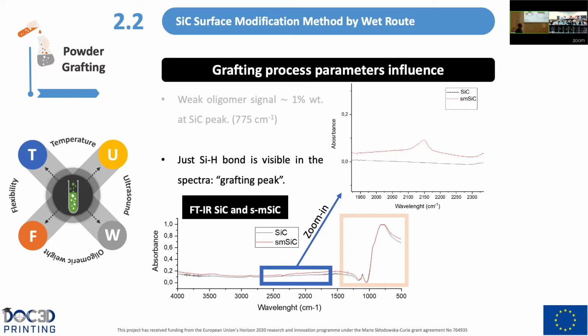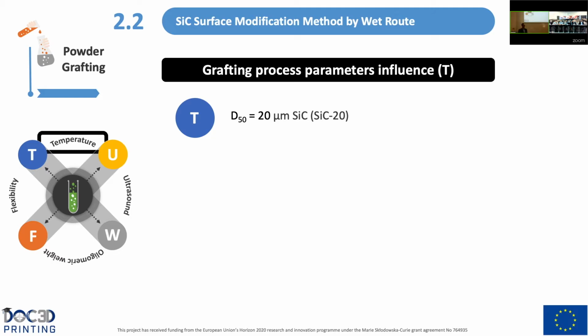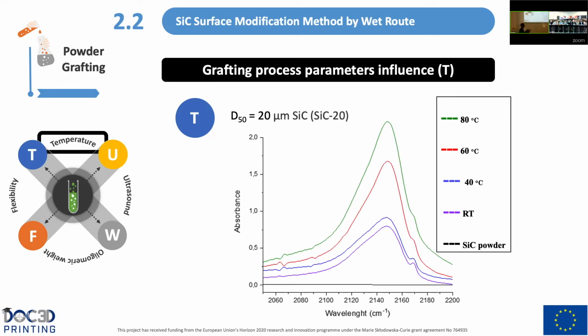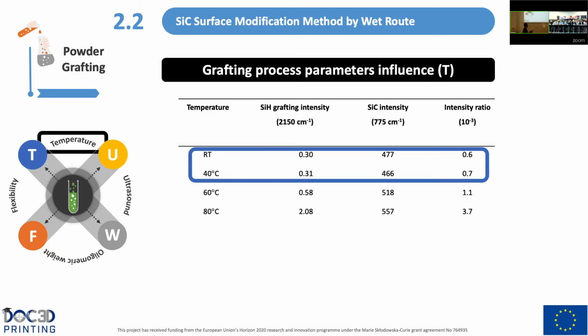So regarding the optimization of temperature, here we were using silicon carbide powder of 20 micrometers, and we were using 4 different temperatures: 80, 60, 40 degrees, and room temperature. And effectively, we can observe in the silicon carbide powder this peak after the process. So regarding the intensity ratio, that's the ratio between the silicon carbide peak intensity and the silicon hydrogen grafting peak intensity, we can see that at room temperature and 40 degrees, we cannot observe an important increase.